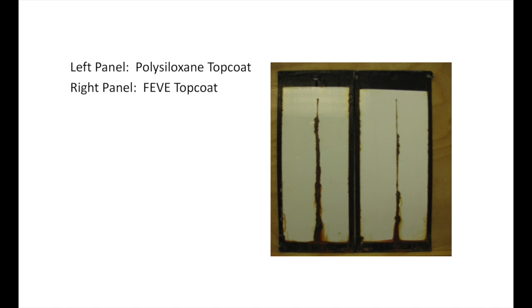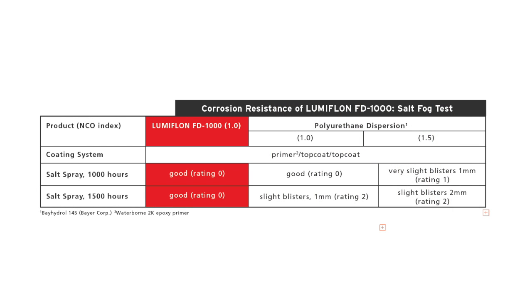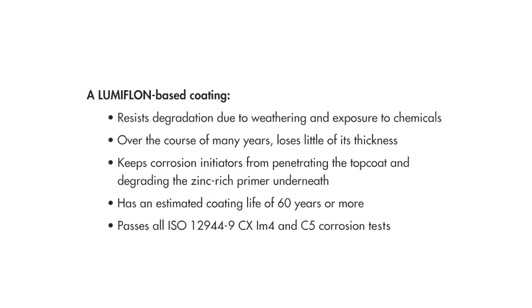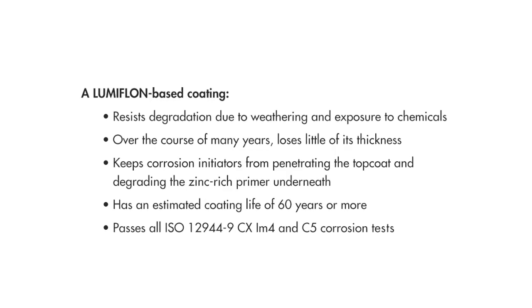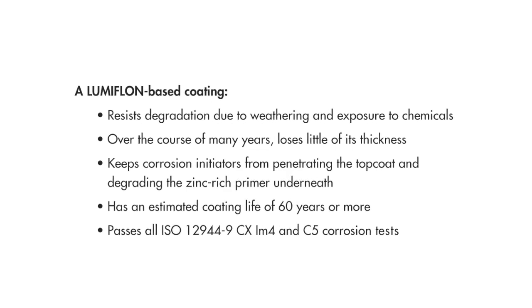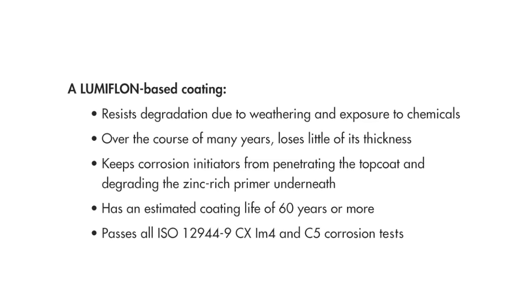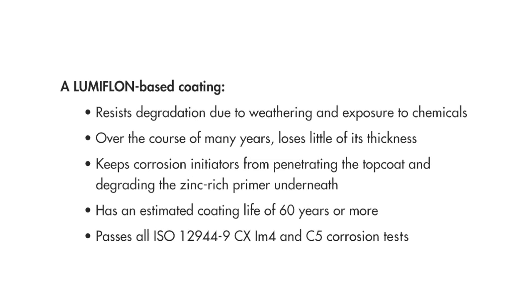Corrosion is a major problem that can dramatically add to a project's life cycle costs, especially for bridges, water towers, and other metal structures. A Lumiflon-based coating resists degradation due to weathering and exposure to chemicals. Over the course of many years, it loses little of its thickness. It keeps corrosion initiators from penetrating the top coat and degrading the zinc-rich primer underneath. It has an estimated coating life of 60 years or more. It passes all ISO 12944-9 CX, Im4 and C5 corrosion tests.